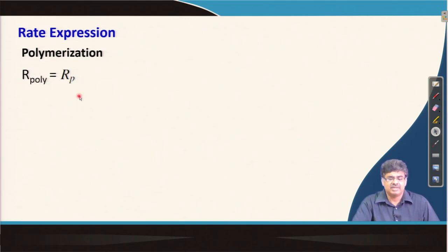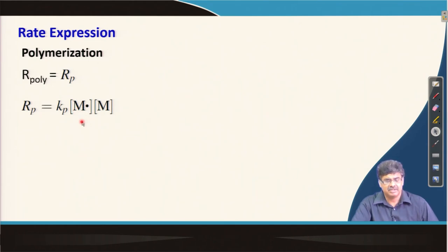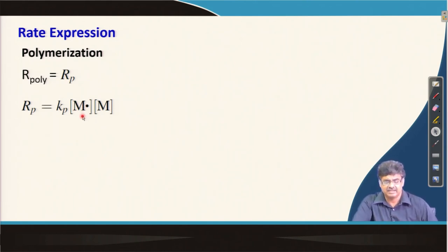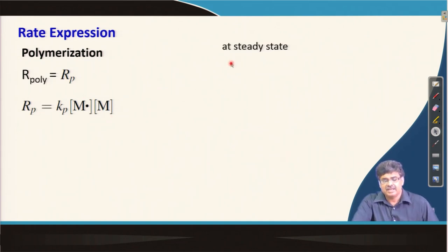The rate of polymerization is given by the rate of propagation, which contains the total concentration of radicals present in the reaction mixture. Determining this experimentally is difficult for two reasons: the concentration is very low — about 10⁻⁸ molar — and these are very reactive, transient radicals. So it is very difficult to experimentally determine this concentration, and hence we use the steady state assumption.